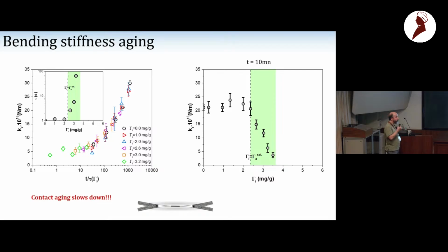The fact that the polymer can slow down the reaction tells us something. It tells us that this polymer is creating a kind of barrier that might prevent ions from coming in. So we think, for example, the calcium ion might play a role. We don't know what the nature of the reaction is. There are some people in the literature who tell you it forms SiO-Si bridges. It could be something else. And we have no clue about what the correct reaction is. But van der Waals brings particles together, and then something happens inside the contact.